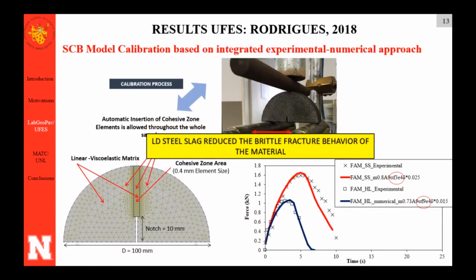And this may represent the material behavior: slag reduced the brittle fracture behavior. So the more brittle the material, we expect a higher level of stress initiation criteria. So slag was less brittle, and it also corroborates with the delta value. It's more ductile, and we have cohesive zones developed earlier in the mixtures with slag.